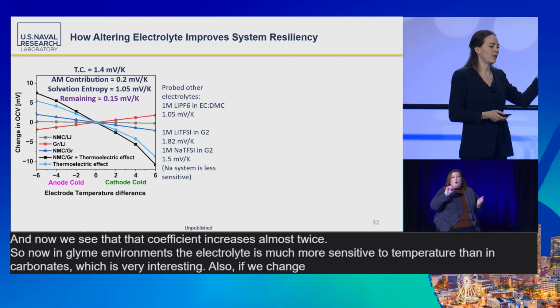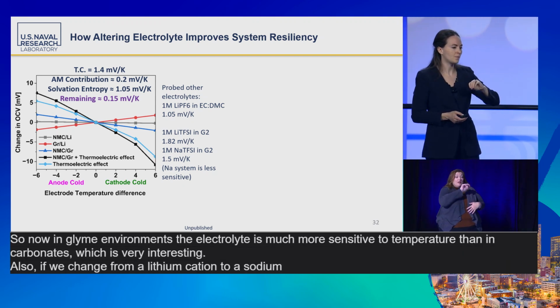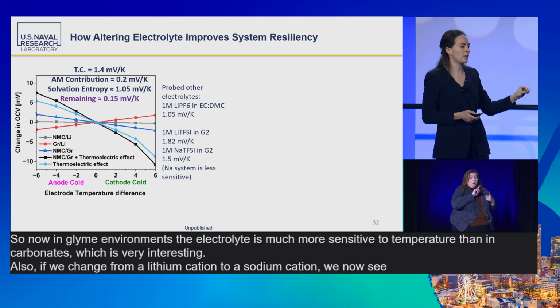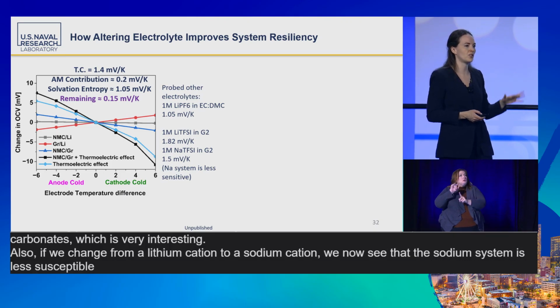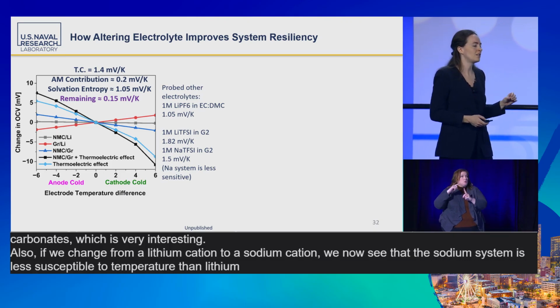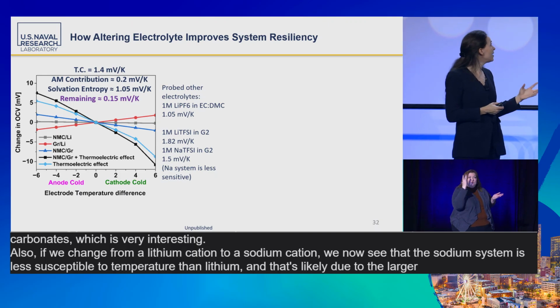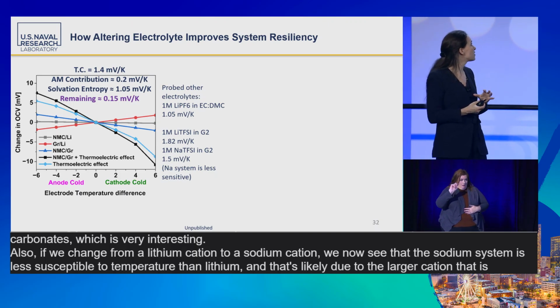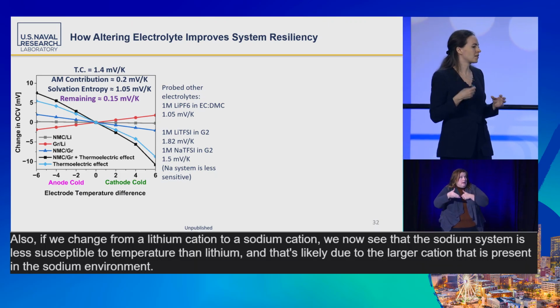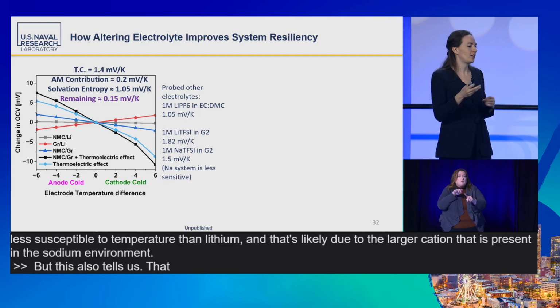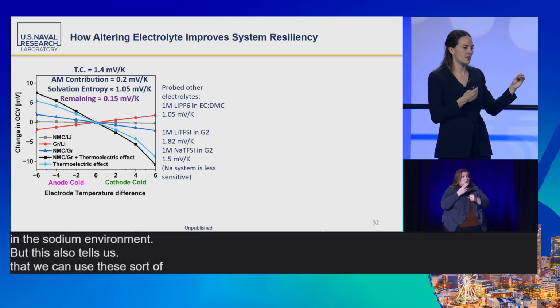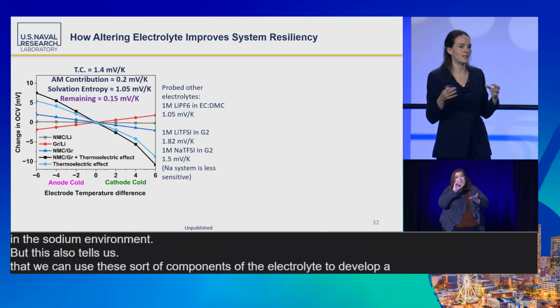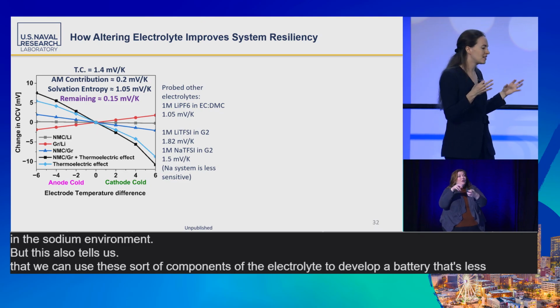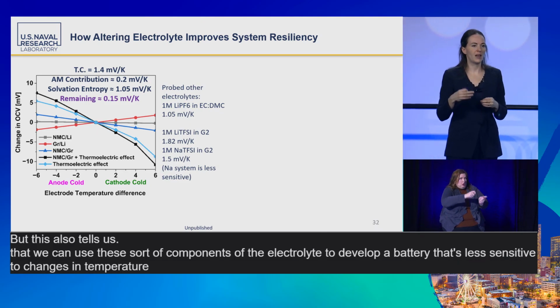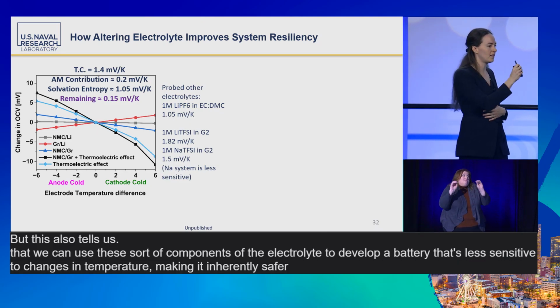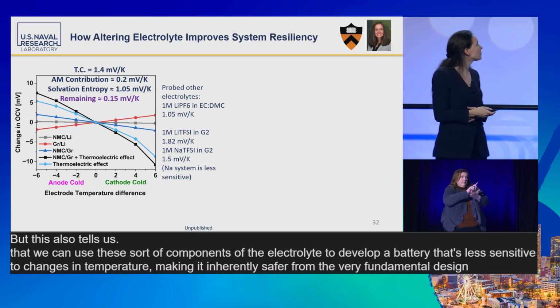Also, if we change from a lithium cation to a sodium cation, we now see that the sodium system is less susceptible to temperature than lithium. And that's likely due to the larger cation that is present in the sodium environment. But this also tells us that we can use these sort of components of the electrolyte to develop a battery that's less sensitive to changes in temperature, making it inherently safer from the very fundamental design.